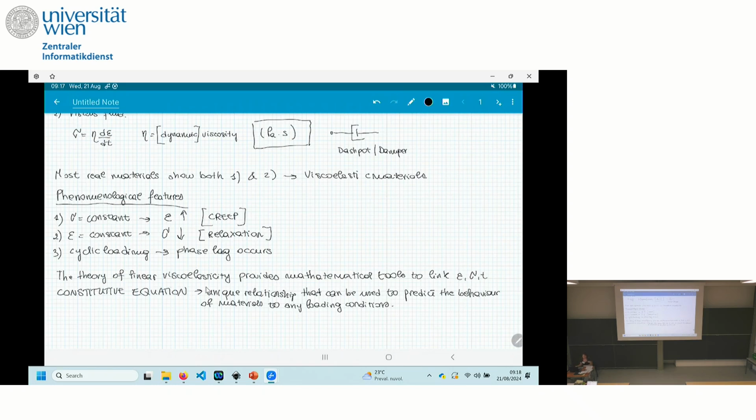You could actually just make your own fitting function. I think this is important. In fact, you will see that when we wanted to prove that fractional models, and we'll see why they are good constitutive models, it was really hard to find in the literature a complete set of data, so both creep and relaxation, or relaxation and ramp, or anything, because normally you find just one test.